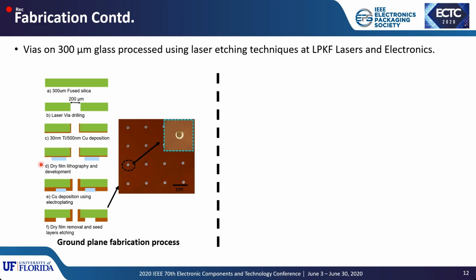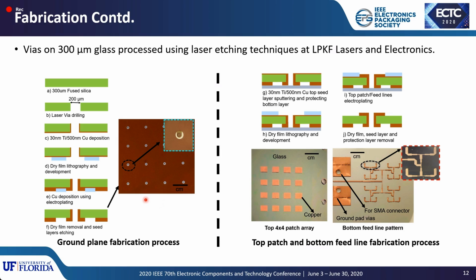In the next step, we use dry film for the lithography and the patterning. And in order to have the metal deposition for thick metal layers, we use the electroplating technique. Once the electroplating is performed, the dry film is removed, and finally the seed layers are removed on the bottom of the substrate and the ground plane is formed. Similarly, the top and the bottom feed line patterns are also fabricated in the same way.